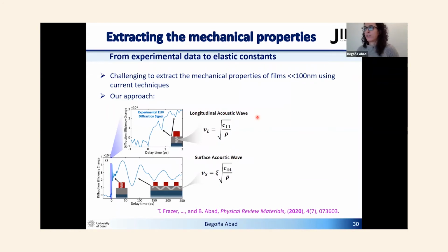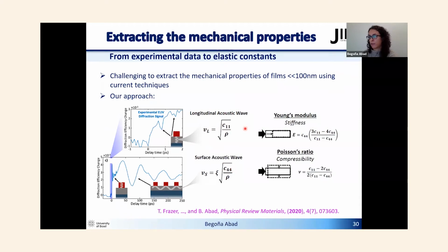As I said before, it's really challenging to extract the mechanical properties of films well below 100 nanometers using current techniques, because the properties are typically coupled with those of the substrate. In our technique, we are able to decouple them by confining the waves within the film, and we are able to extract both Young's modulus and Poisson's ratio. From the echoes that I was explaining before, the reflections from the interface, we are able to extract the C11 component of the elastic tensor. And from the surface acoustic waves, we are able to extract the C44 component. From these components, we can finally extract the Young's modulus and Poisson's ratio, which tell us about the stiffness and compressibility of our materials.